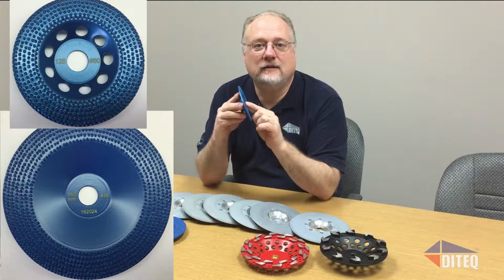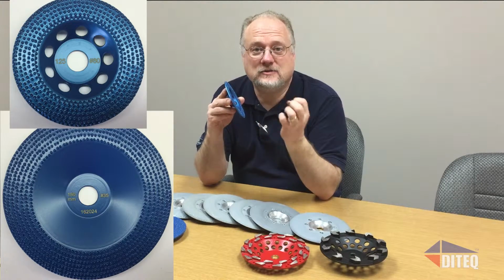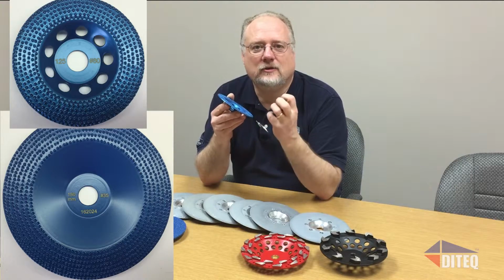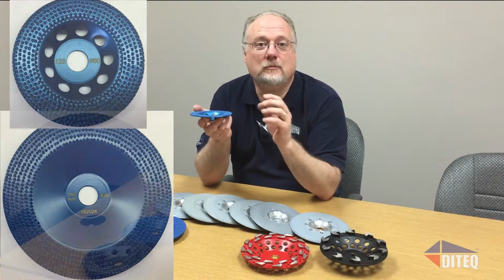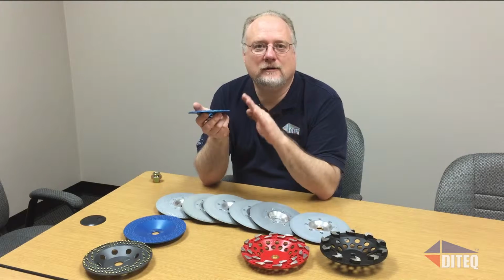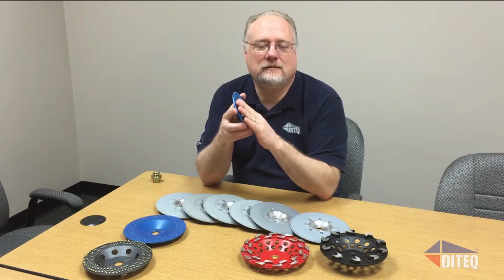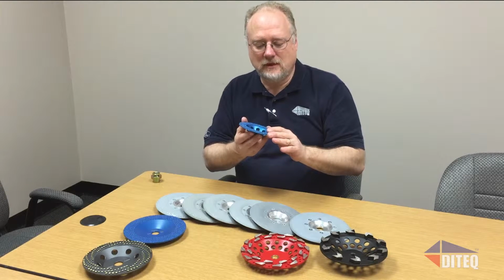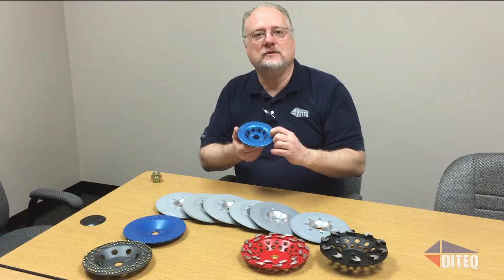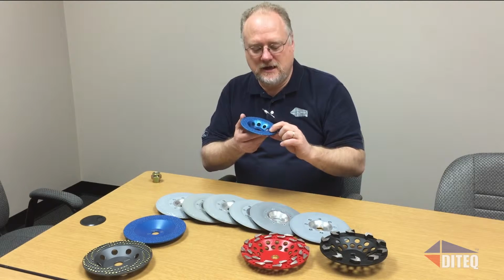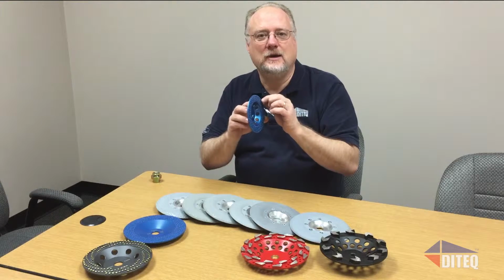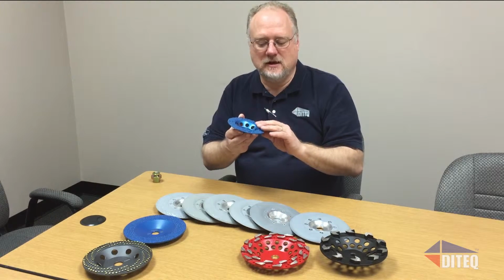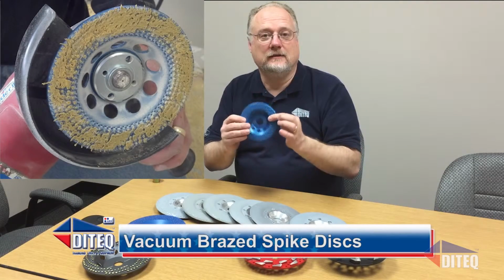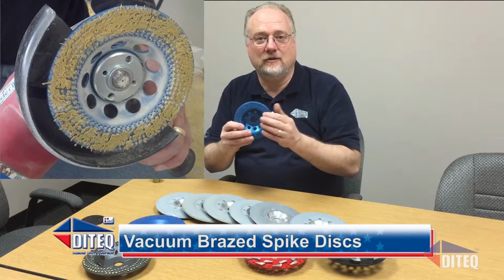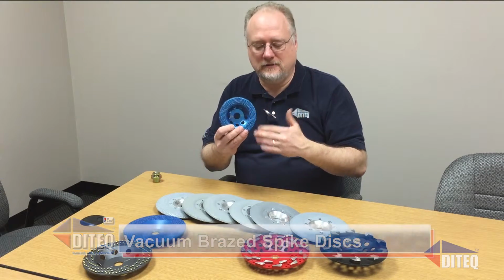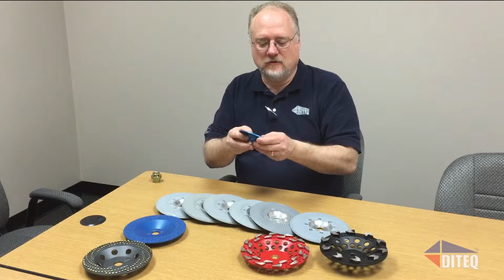A big diamond has an advantage to cut through the coating and to remove more material, but it's also very fragile. How diamonds are cut is they break along natural points, weak points on the diamond crystal itself. So these are small diamonds that are very, very tough, held together with a vacuum braze, and they're put into a spike pattern, so they become big, large protrusions. So these cup wheels don't plug up with debris, glues and coatings, mastic coatings, and they cut nearly as fast as a single layer diamond would. But these are very, very coarse.